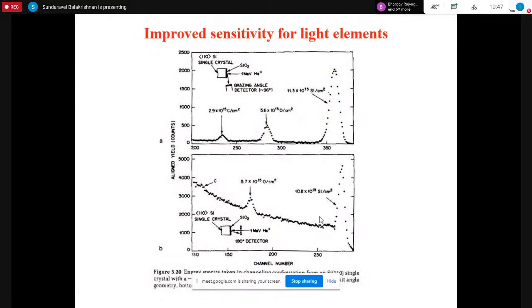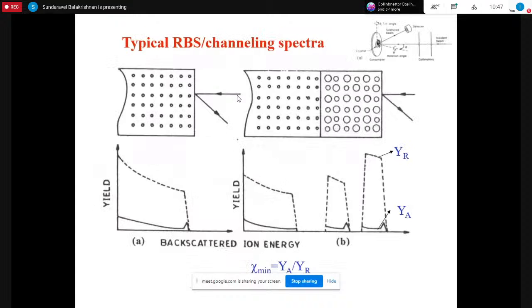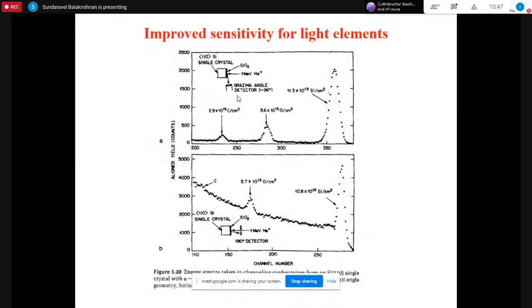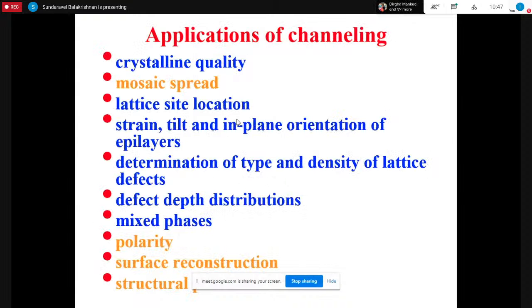And suppose you have some very thin silicon dioxide or some other thin material on your sample. Under the aligned condition, compared to the random direction, if you see the backscattering in the aligned direction, whatever background is coming from the substrate will be much less, and one can have enhanced sensitivity for light elements using this technique.